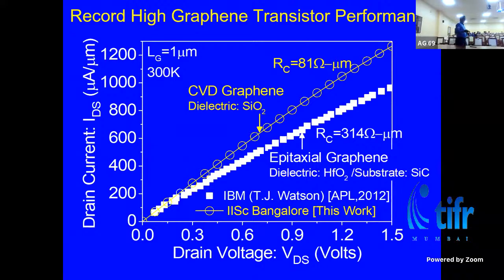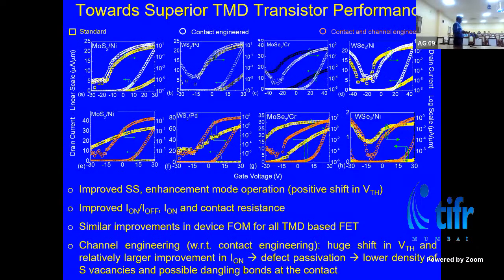Okay, so if you compare our data, which is CVD graphene directly on silicon oxide, right? Silicon oxide is bound to have a lot more scattering in the channel compared to other dielectrics, say aluminum oxide with a silicon carbide substrate. But what we have is our engineered contacts and much better technology, with the technological problems addressed in a much better way. And what we show is 20% better than the best reported so far, that was by an IBM device, right?